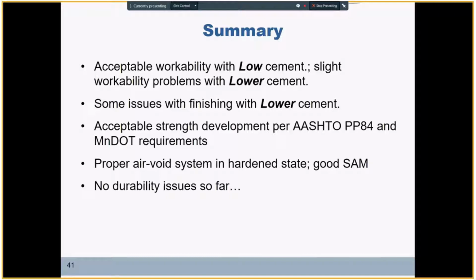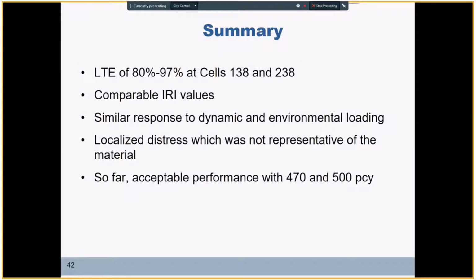Very good air void system, good durability indexes, and the only concern regarding durability was the potential for oxychloride formation, which again is because of the binder composition, not the cementitious material content. The in-situ measurements - FWD data, IRI measurements - all indicate comparable, acceptable performance for these two mixtures. No abnormal behavior so far, nothing that could be a red flag or warning that we cannot go with these cementitious material contents for future construction projects.